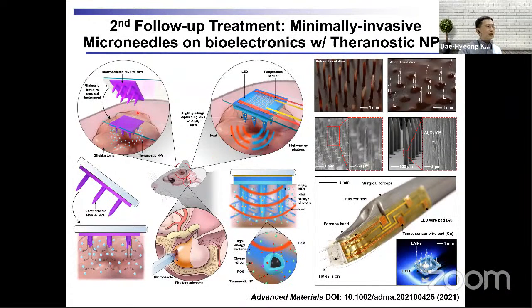And to achieve this strategy, first, we make a contact of this biodegradable microneedle to the target region. Then the needle will be dissolved as shown in this image, and the loaded nanoparticles will be delivered to the target region. And after that, we can just switch the microneedle into the light guiding microneedle integrated on the LED. Then the LED will generate high energy photons like UV photons, and those UV photons will be guided by this microneedle. And this microneedle includes aluminum oxide microparticles.